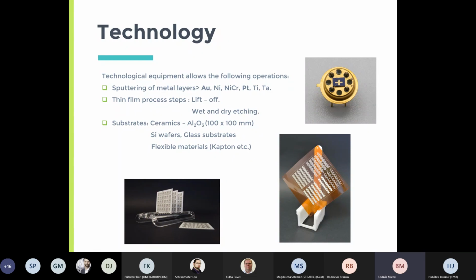The technology we use, one more time, is sputtering of metal layers. We prepare these layers for research institutions or for ourselves, and with our colleagues, we use this especially for gas sensors, developing with new materials, nanomaterials, single wall carbon nanotubes with some dopants or another material. We use ceramic substrates, silicon wafers, and glass substrates. These are our typical substrates. Sometimes we are able to produce electrode structures on flexible material. You can see here the Kapton foil.